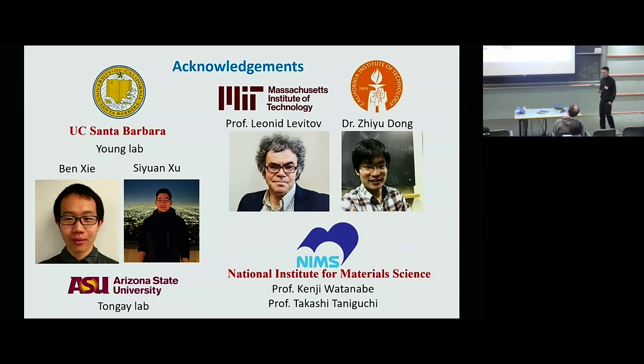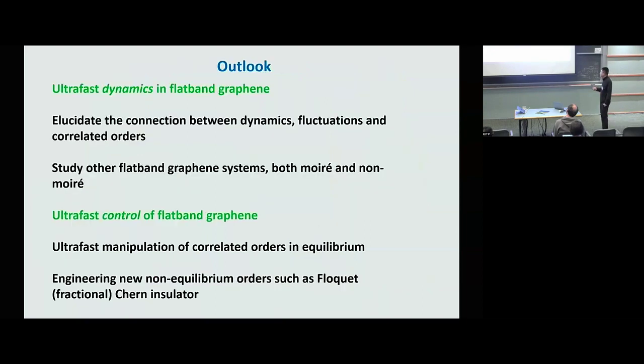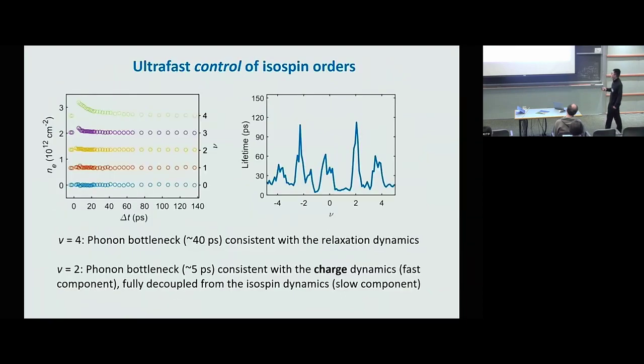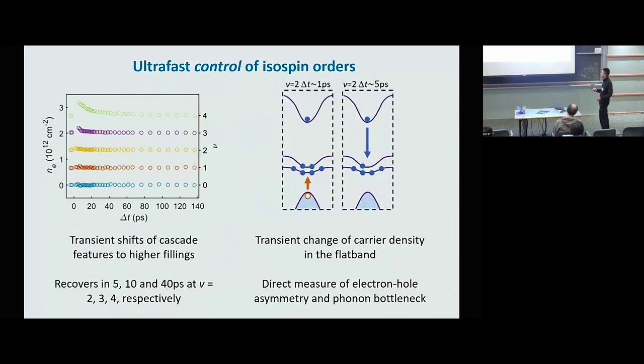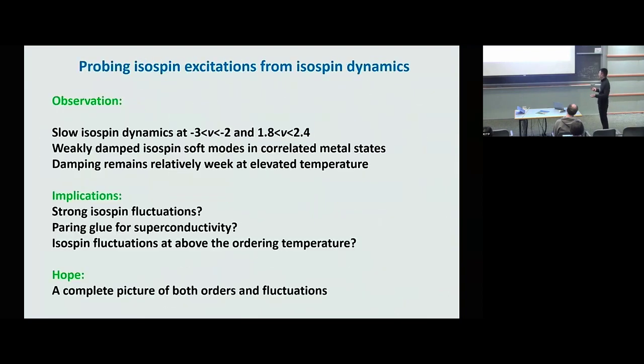I wonder whether you can see any SU(4), SO(4) symmetry from your measurement at all? So are you asking whether we can infer some ground state? No, I mean, this mode should encode some of the symmetry, right? For example, it should have some degeneracy due to the symmetry. So I wonder if you break the symmetry manually, whether you split the modes into more modes or something. Yeah, that's a good question. Indeed, if we change the symmetry, the energy of the mode is supposed to change a lot, depending on what the mode is, and also the strength of fluctuation, the dynamics, and the damping should also change.